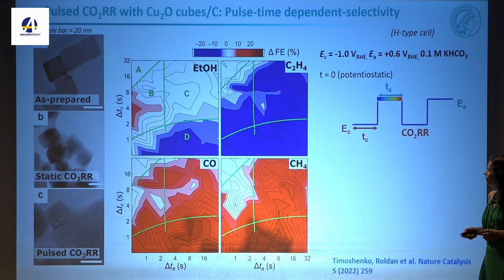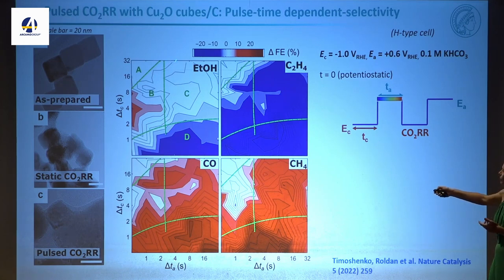And as electrochemists, we could make this diagram. Ethanol production, ethylene, CO, methane. The change in the color is how much more in red or how much less in blue we are making, with respect to when we run these catalysts under potentiostatic conditions, only at constant -1 volt. If you do it at constant -1 volt, ethanol, this is in white, there is no difference. If you start applying these potential pulses and you get more ethanol, then you see it in red. If you get less, you get it in blue. So these diagrams show you that there is a particular length of the anodic pulse and the cathodic pulse where we are making a lot of ethanol.